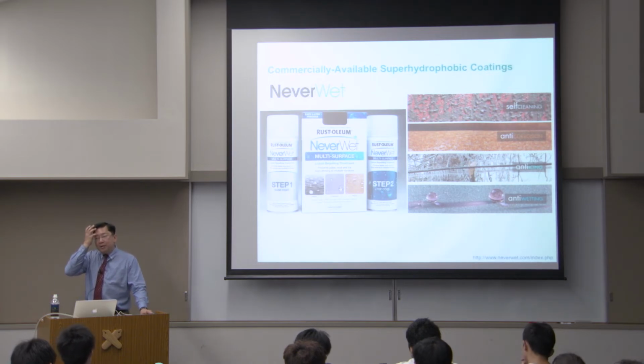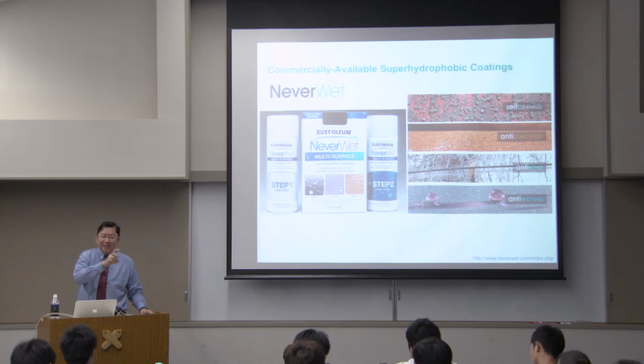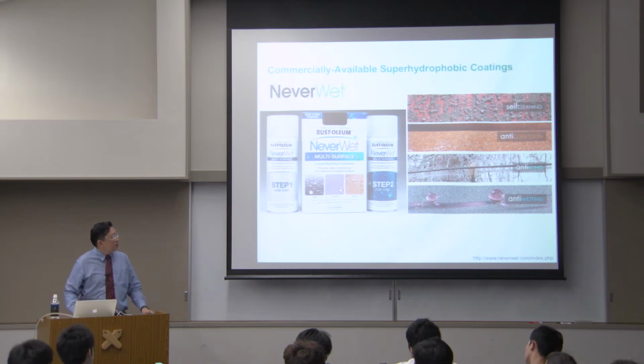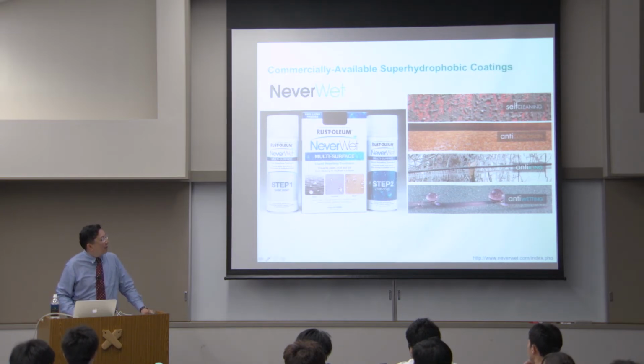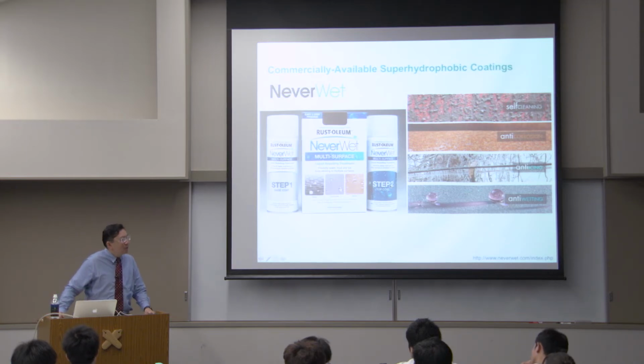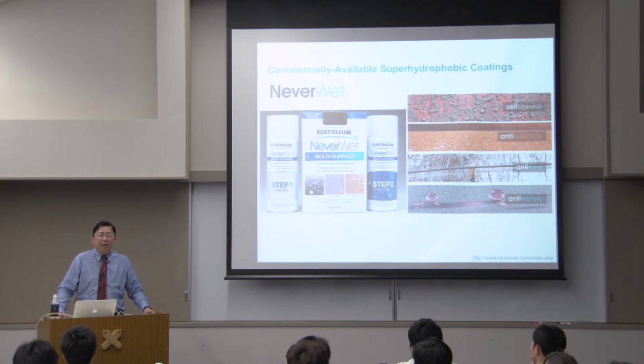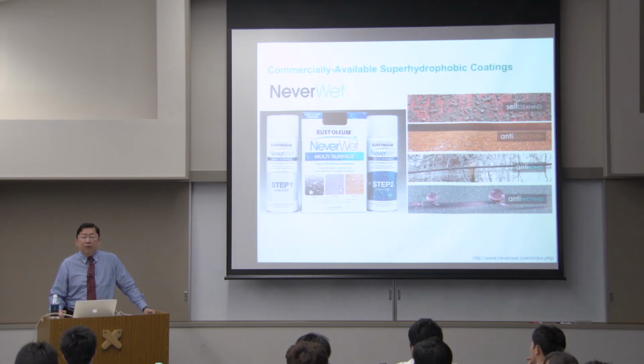After you prepare the primer, you then spray the second part, which we have tried to deformulate. It actually contains silica nanoparticles, we've found. But you can deformulate this. This essentially creates a rough surface, a hierarchy of roughness, and perhaps they included some silane agents that have low surface energy.